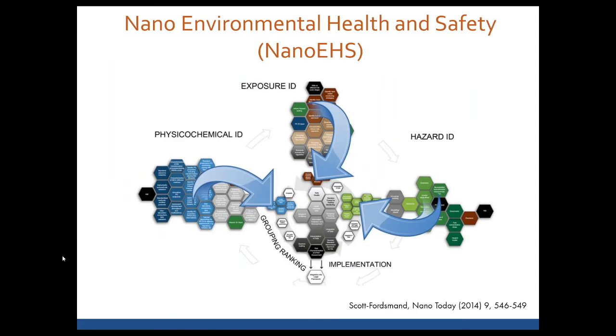So going back to our map of how to delegate risk, the last component I haven't talked about is exposure. Most of the experiments to date have been done with pristine systems, because you really want to try and find out what's going on. If you start with a very complex material, it's very difficult to determine which component of that matrix or that complexity is causing the effect. So there's been a lot of pristine studies, but that's really not what we're exposed to.